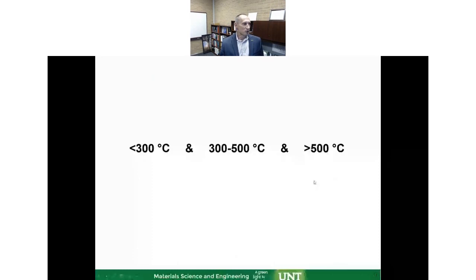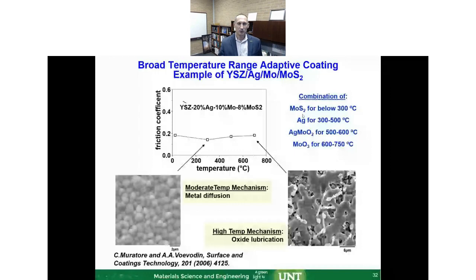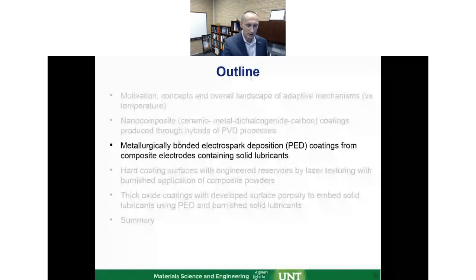All right, so I showed you 300 C, moderate temperature, and about 500 C. Can we combine this all together? Yes, we can. And now this comes back to the structure which we have: zirconium oxides, silver, molybdenum disulfide. These are the data points at different temperatures: room temperature, 300 C, 500 C, 700 C. The different mechanisms at different temperatures we discussed, but it keeps the friction right in a band at this point. So it is working, and I think I'm done talking about some of that PVD coatings.